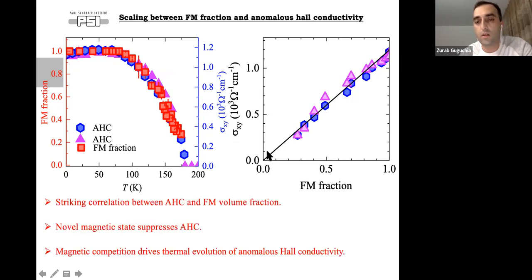So what we have is this striking correlation between these two topological quantities and the magnetic fraction, which means that the novel magnetic state actually suppresses the Hall conductivity, and that the magnetic competition between these two structures drives the thermal evolution of the topological Hall conductivity. So this quantitative link between these two quantities was very exciting to see.